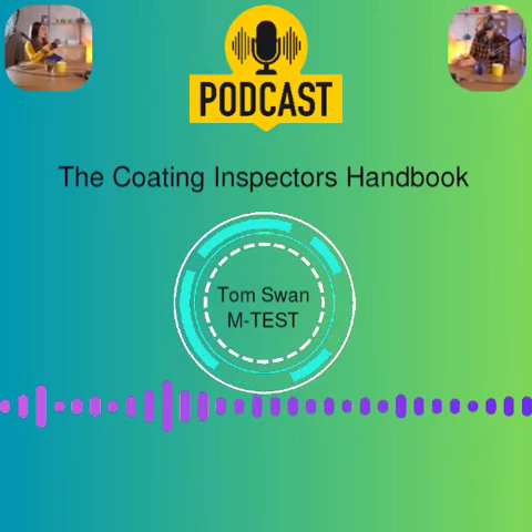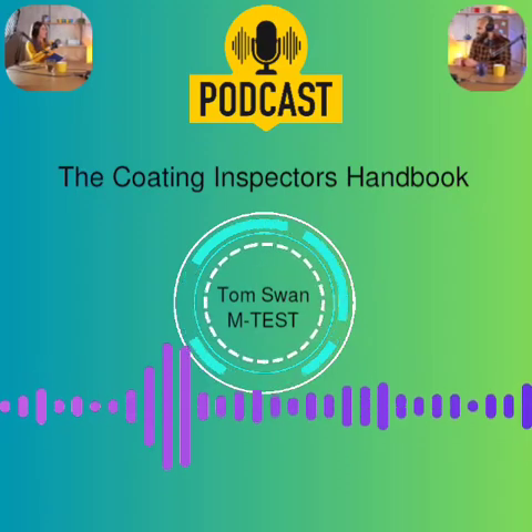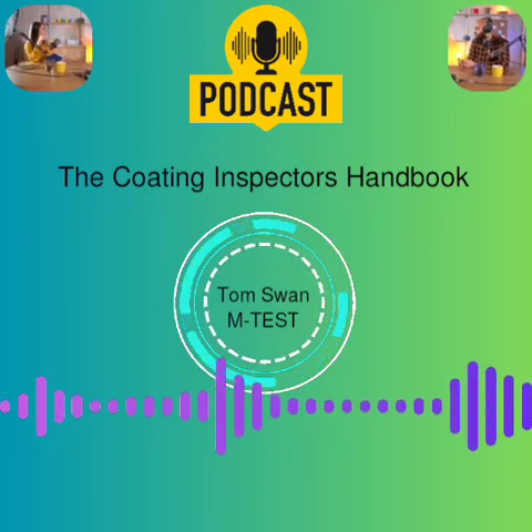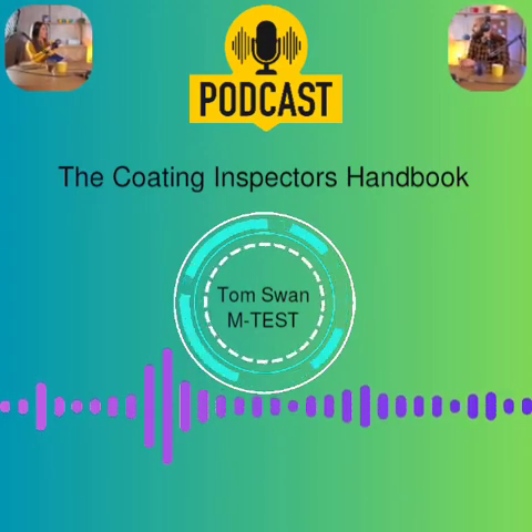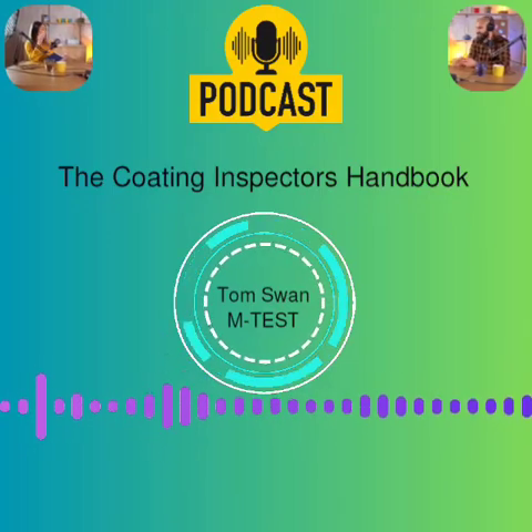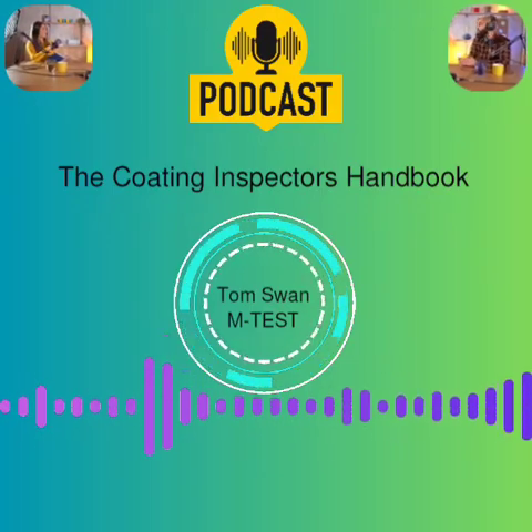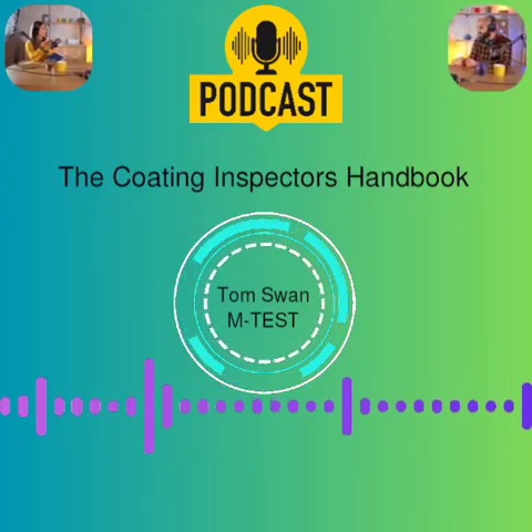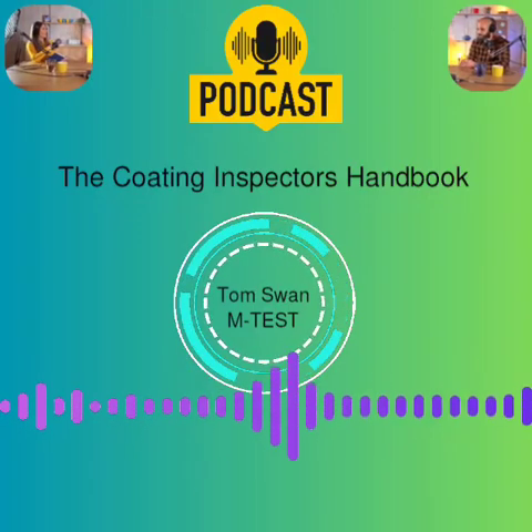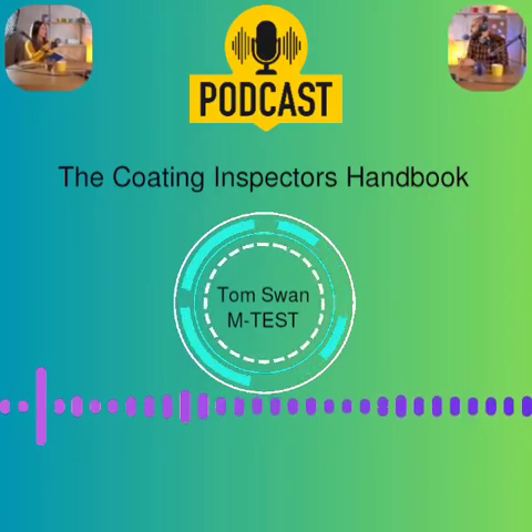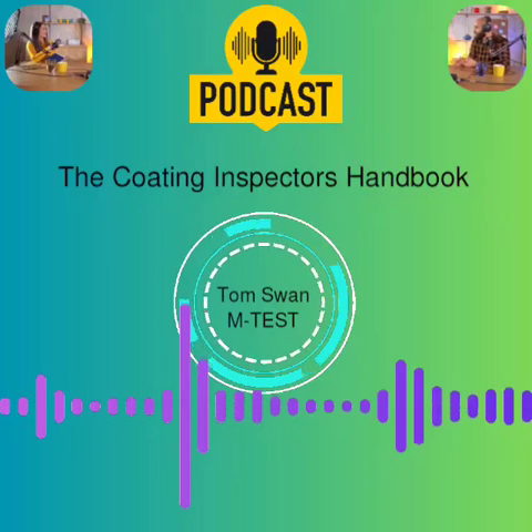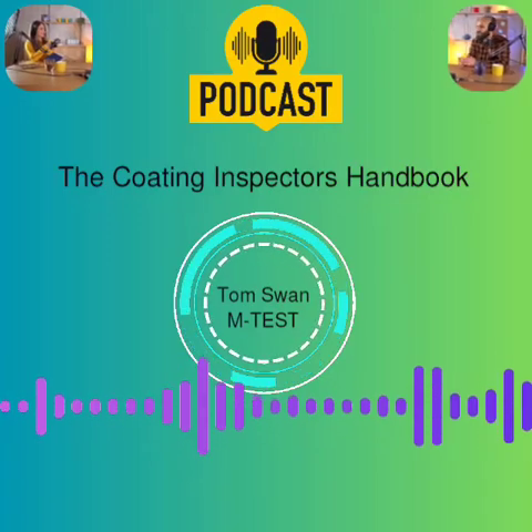Exactly. Using standard methods. ASTM D4417 covers the main field methods. Method A is visual comparators, B is profile gauges, C is replica tape. Let's look at Method A, visual comparators. These are like little swatches, metal or plastic, showing different profile ranges created by different media: sand, shot, grit. You hold it next to the blasted surface, use a magnifier, and compare visually.